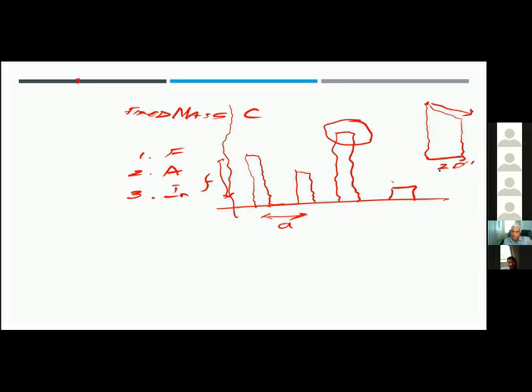So the question of potential doesn't arise because I have fixed my carbon mass based on the surface area and the case depth. Now, how I distribute it is a matter of the algorithm, which takes the case, the geometry and the loading. I can decide different levels of how much I initially start high, then I can come low.